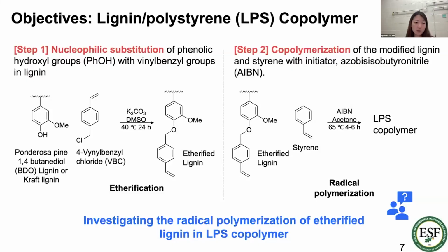We use VBC, which is very similar to the structure of styrene, and we modified the lignin, called etherified lignin. Once we prepare the modified, etherified lignin, we use styrene and initiator to prepare the copolymer. This process is radical polymerization, and we newly introduced a solvent into the polymerization to dissolve the etherified lignin produced during the process. The purpose of this study is to see how the lignin modification for radical polymerization with the styrene structure together is successfully introduced into the polymer system.